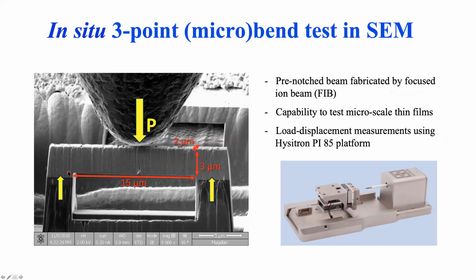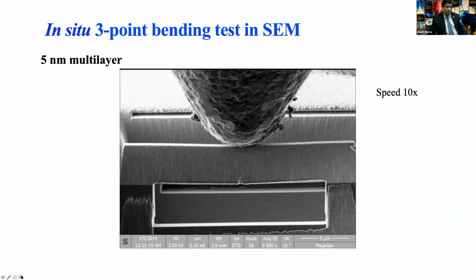Okay. So all of this was just uniaxial compression and then tension. One of the tests that was missing was a test that would measure some kind of a crack growth response. It's difficult to do in thin films. So in collaboration with a group at Los Alamos, we have done these kinds of bend tests where you grow film thicker, up to 5 microns, and then we can make this kind of a 3-point bend test, create a very sharp notch, and then do a bend test in situ in SEM.